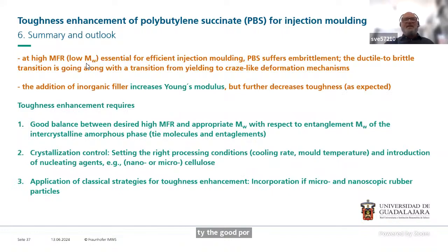The problem is that at high melt flow rates, which means low molecular weight, PBS suffers embrittlement. We have a ductile to brittle transition, and this goes along with a change from yielding to craze-like deformation mechanisms. Even with inorganic filler addition, it gets even worse, as expected.